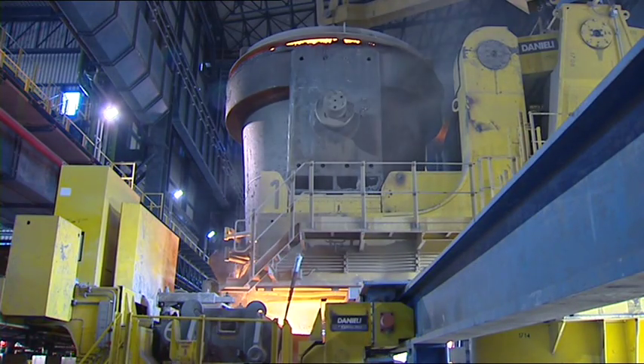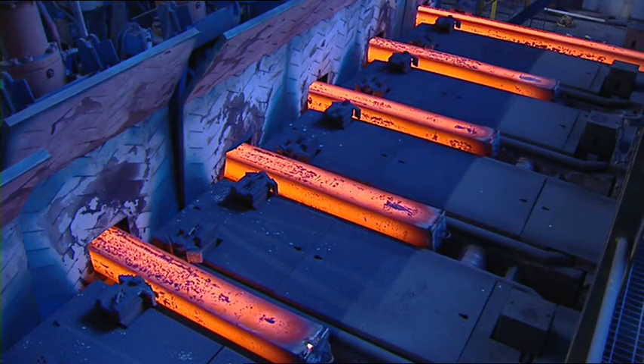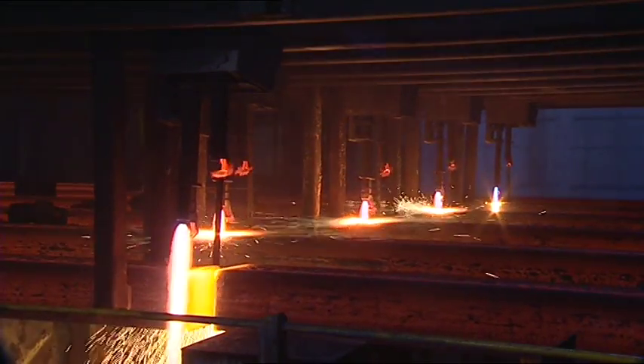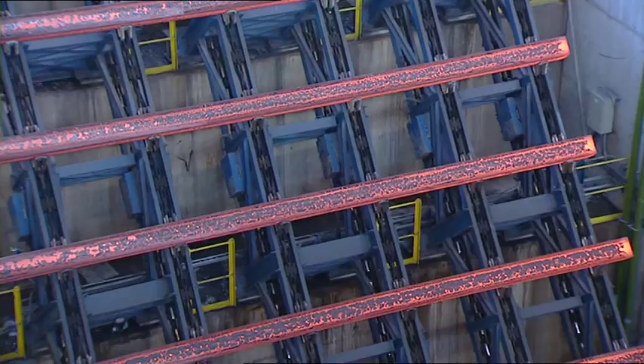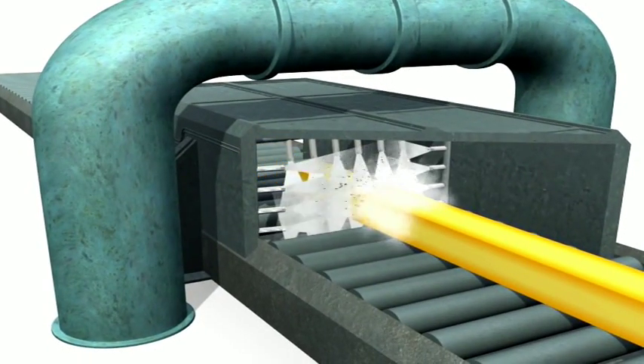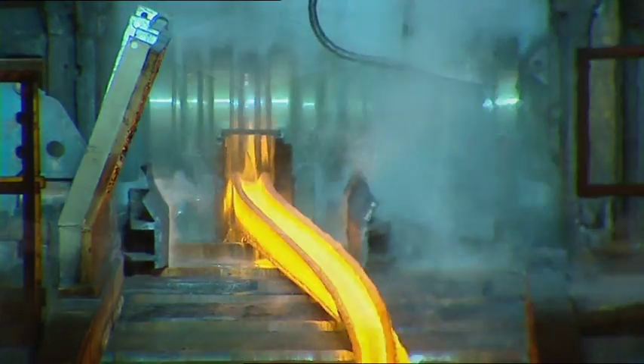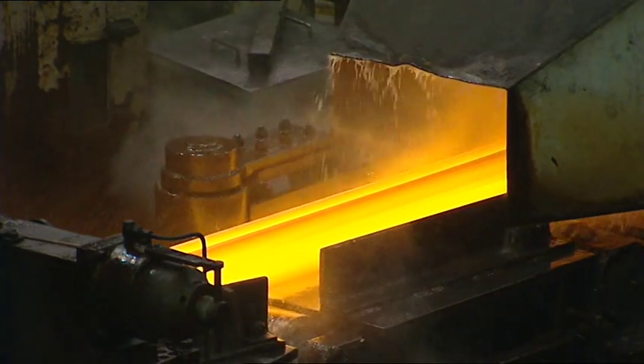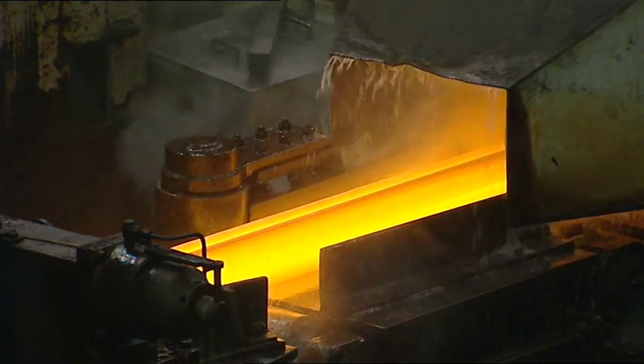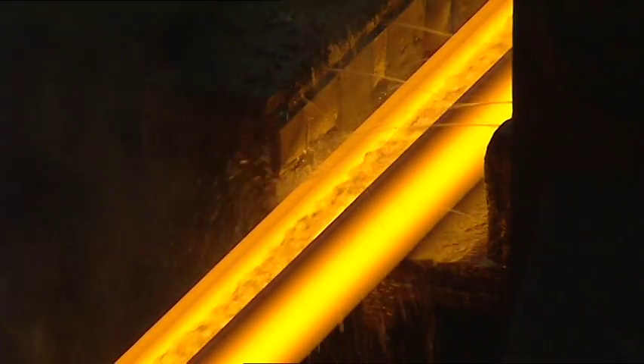In recent years, we have also invested £20 million to develop steel-making facilities on our Scunthorpe site for rail manufacture. This produces steel to exacting standards, which is supplied to the mill as high-quality continuously cast blooms ready for rolling. The blooms are reheated to rolling temperature and then undergo high-pressure descaling before initial size reduction in 2 reversing stands. Secondary high-pressure descalers ensure that the surface is maintained in a clean condition throughout the rolling process. This produces an excellent surface finish on all rails.